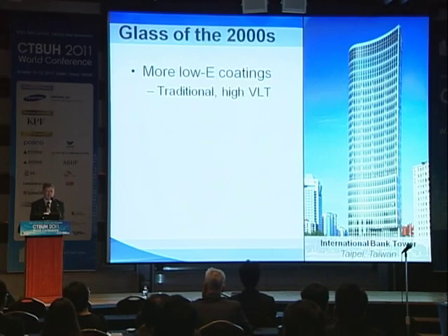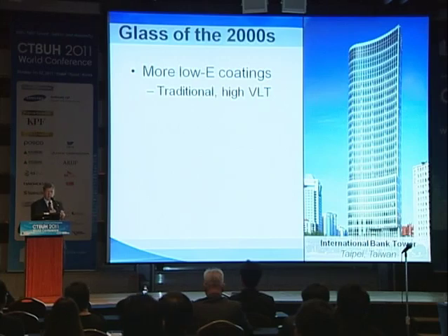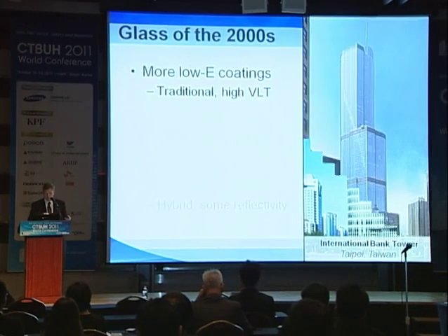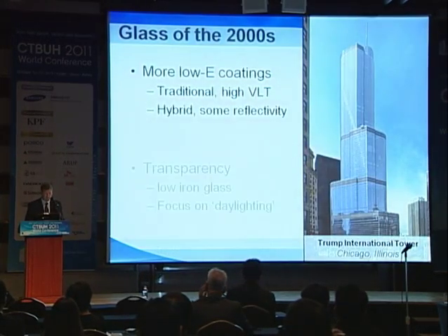A typical insulating unit with 6-12-6, no coating on it, clear glass, has an interior and an exterior reflectivity of about 14%. When we added some of our low emissivity coatings, it dropped that reflectivity down to 11 and 12%. So they tended to make that glass go very, very dark in the opening until you dropped a blind, and if you dropped a blind, then you saw the color of the materials. Where the hybrid coatings, because of that degree of reflectivity, you are going to get some sparkle, some life to the glass, but you still get that transparency. And again, you can see that in some of the buildings we have here today.